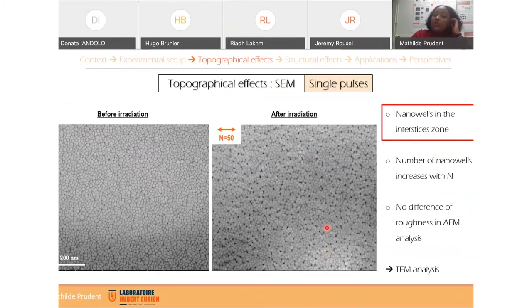So here you can see the first results for the single pulse irradiation. To the left, we can see a zone of a non-irradiated sample before irradiation. And after, we can see the same zone after irradiation with 50 pulses of laser. So we can see that we have the creation of nanowells in the interstices zone that we talked about before. And this number of nanowells increases with the number of pulses.